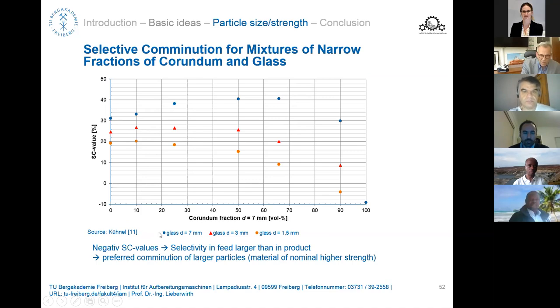To start with the glass beads of 7 millimeters compared to the corundum fraction also being 7 millimeters in the different mixtures, you can clearly see that in the initial case with a small number of glass beads, the number of broken glass beads is smaller, while at about 50% glass beads and corundum beads, the percentage of broken glass beads appears to achieve a maximum, and then it drops again. That is quite typical, as expected for the softer fraction. This is something also seen by Fürstenau, if you have the same size and just different materials.